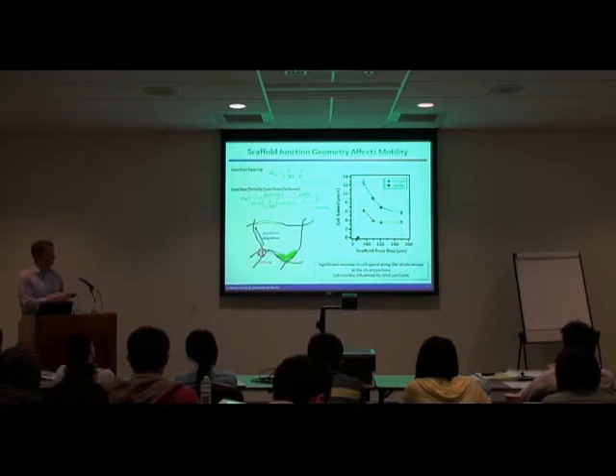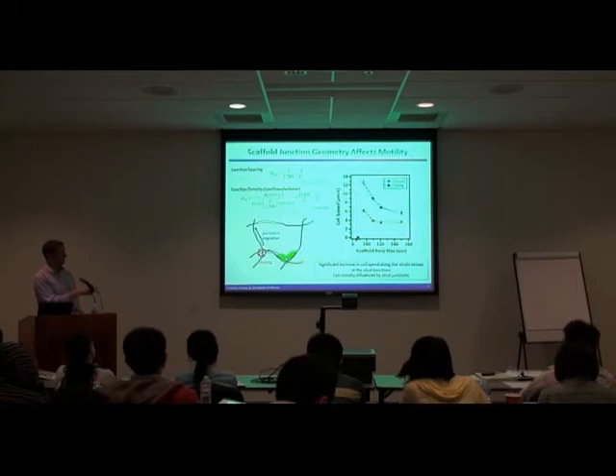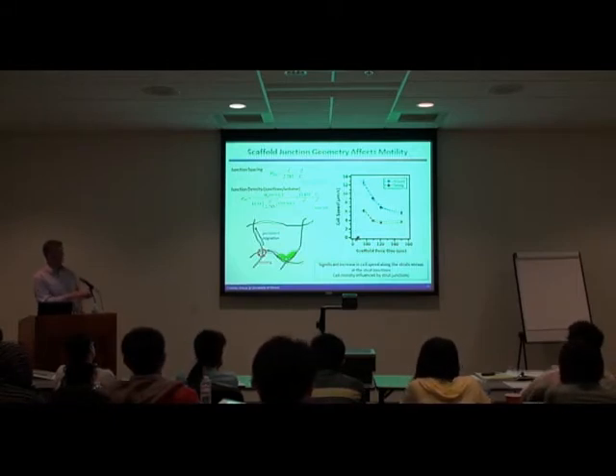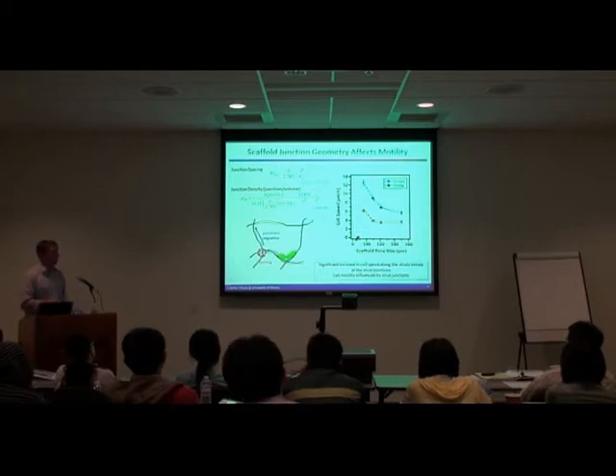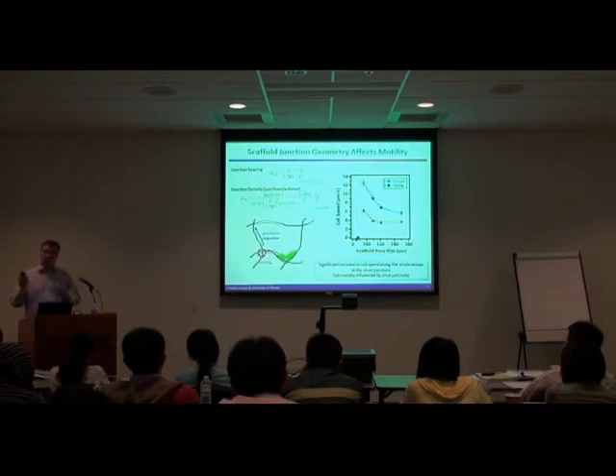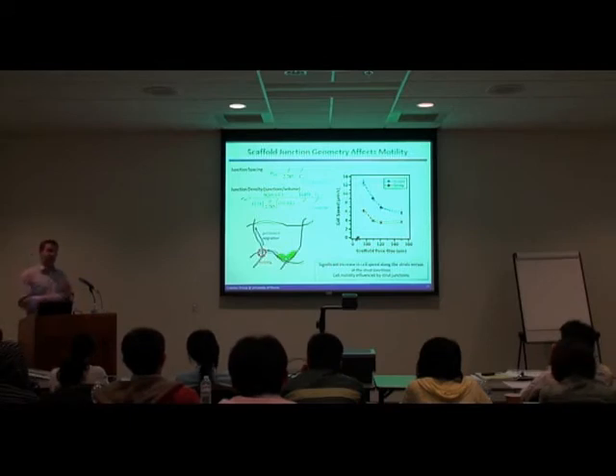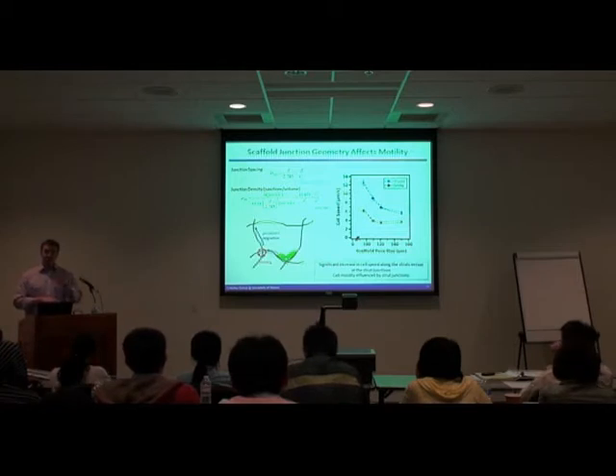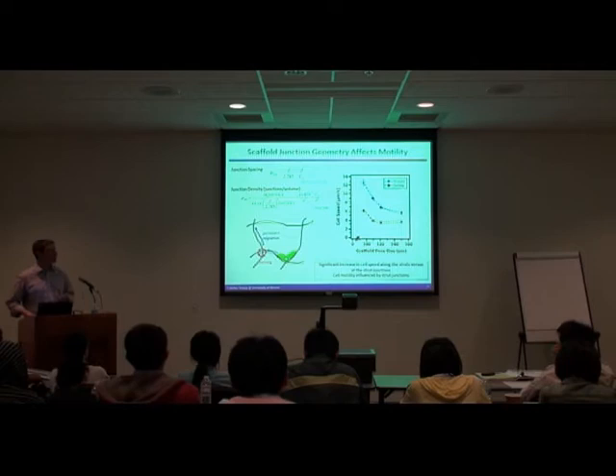And saw that not only were there huge differences in migration along the fibers due to pore size, but also there were significant differences in the migration of cells at the junction points that also scaled with the pore size of the scaffold. So what this allowed us to say is that, we don't have this totally nailed down yet, but at least having a modeling framework and a homologous series of standardized materials gives us a running start. It's starting to make quantitative measurements of exactly what is going on from a mechanistic perspective, how cells behave inside 3-dimensional materials.